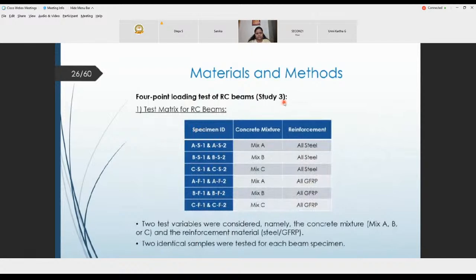In study number 3, we actually tested on macro scale reinforced concrete beams, actual reinforced concrete beams. We used two variables for these beams, namely the concrete mixtures, mix A, B, and C, already defined, and also the type of reinforcement. We tested specimens with all steel and all GFRP. When we say all, we mean longitudinal reinforcement in the tension side and the compression side, and also the stirrups.